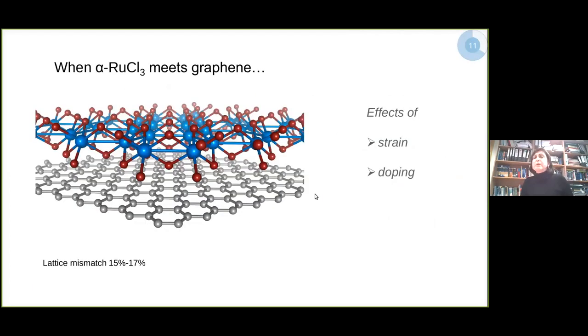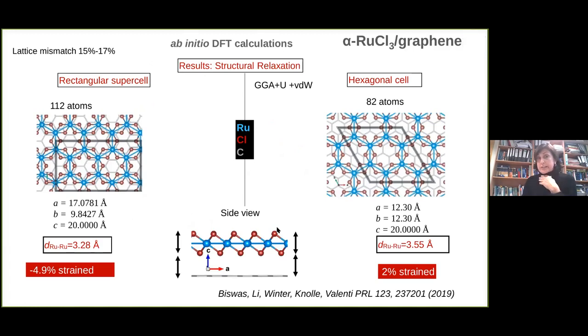So let's see what happens now when we bring these two systems together and we form a heterostructure, where we are going to expect, as I was mentioning, effects of strain in this system, as well as doping, so charge transfer. So of course, the first way to try to understand what happens here is by doing an ab initio density functional theory simulation of this system. So basically, the idea is to take slabs, superstructures of these two systems, bring them together, and then test various different slabs. Which of those is the one that is energetically most favorable? And here I'm showing two of the possible slabs that we considered in order to find which slab is the one that is energetically most favorable.